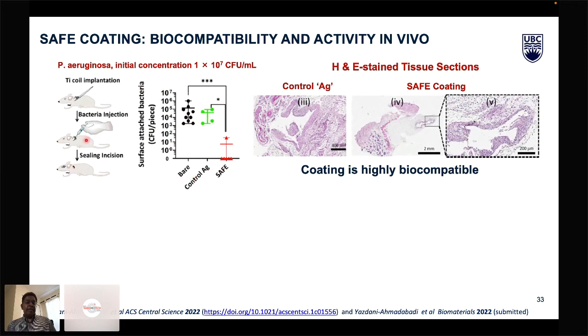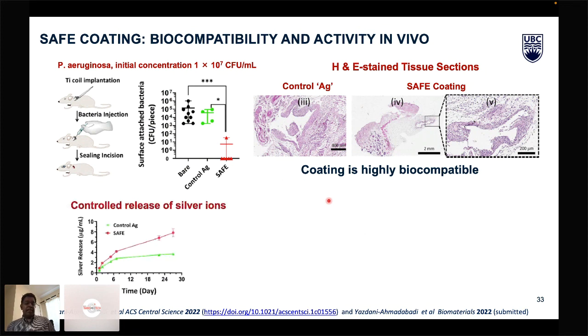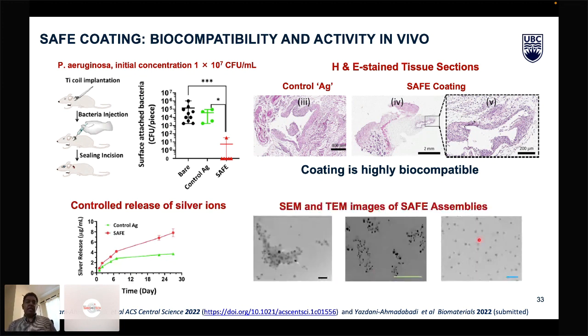And here the titanium implant is implanted and infected with bacteria, and you could see several orders of magnitude decrease in the bacteria count. And also this surface is really biocompatible. That is one of the challenges for silver. And what we found is that when the coating is placed in this hydrophilic environment, you can make it really biocompatible and non-toxic. And the reason is that we were able to achieve controlled release of the silver, and in situ formed silver nanoparticles are used here, and that makes this controlled release possible.